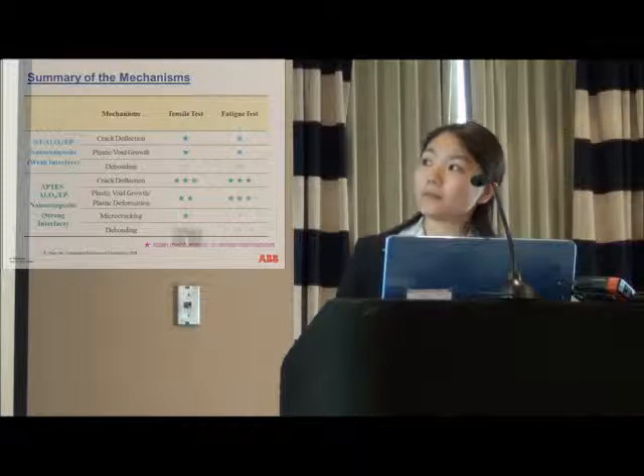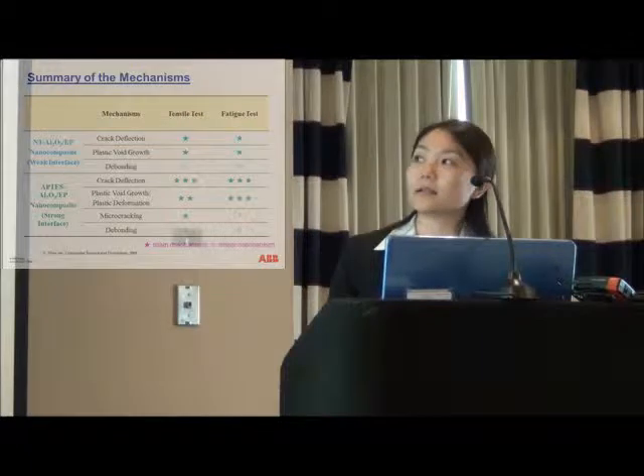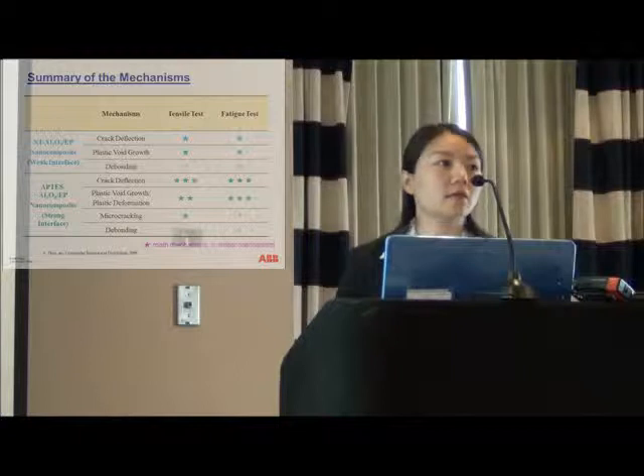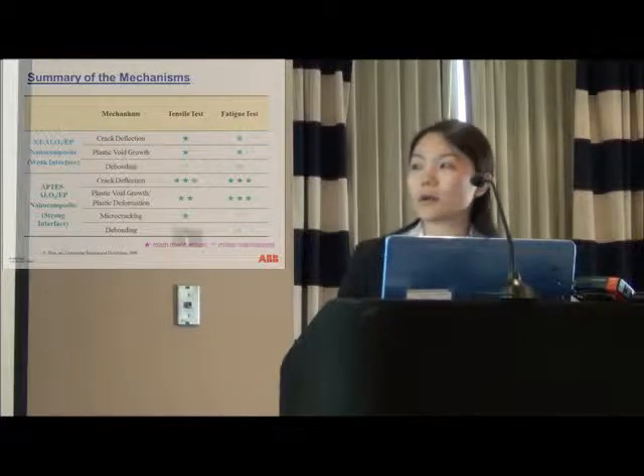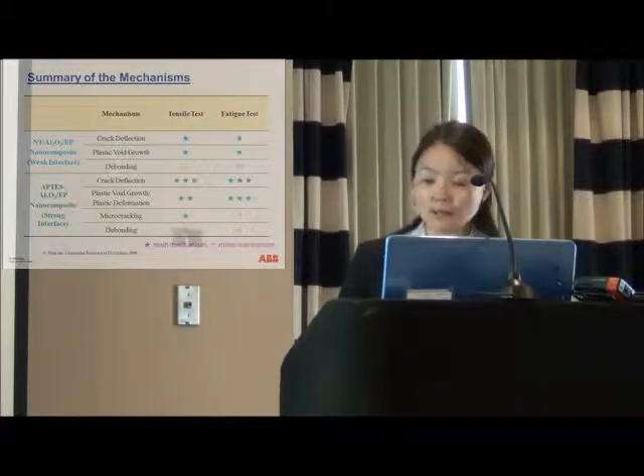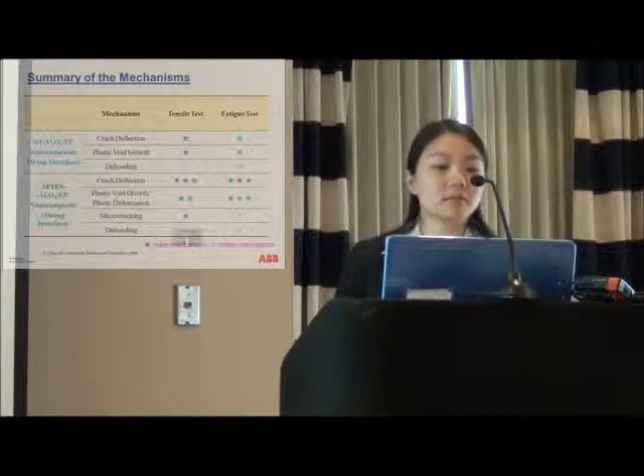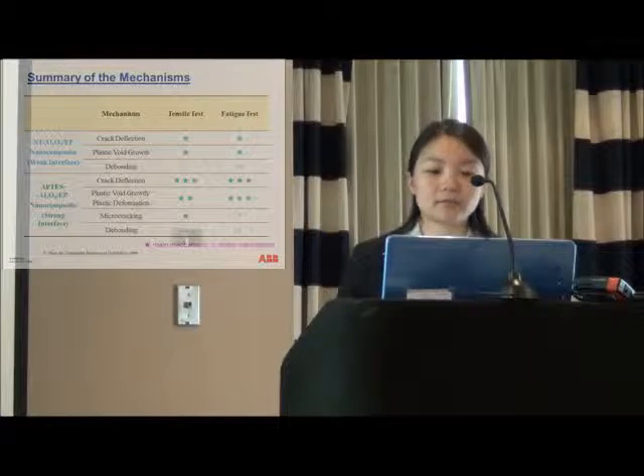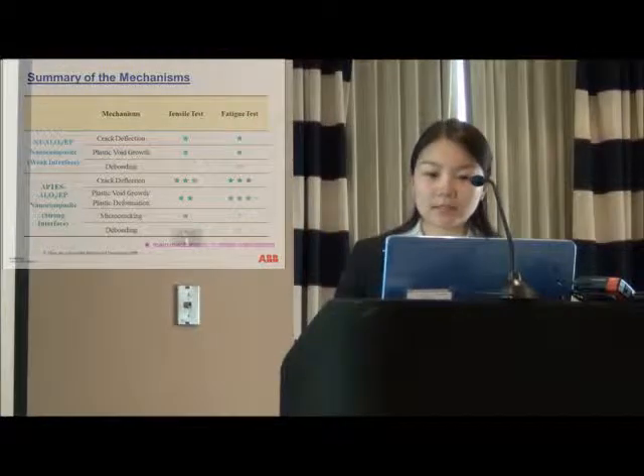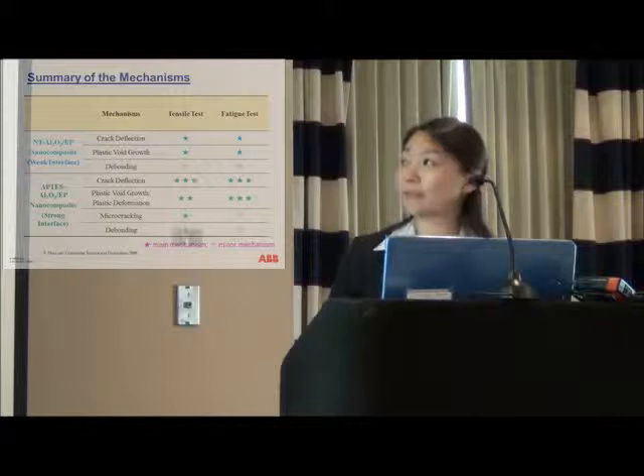Here, for both non-treated and treated nanocomposite: for the non-treated, you have a weak interface between particle and matrix, and for the treated one, you have a stronger interface. In both cases we see crack deflection and plastic void growth, but they look a little bit different.